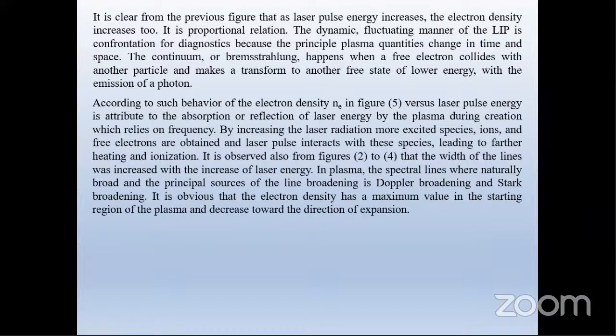It's a proportional relation. The dynamic fluctuation manner of the laser-induced plasma is a challenge for diagnostics, because the principal plasma quantities change in time and space. The continuum or bremsstrahlung happens where a free electron collides with another particle and makes a transition to another free state of lower energy with the emission of a photon. This behavior of the electron density in figure 5 versus laser pulse energy is attributed to the absorption or reflection of laser energy by the plasma during creation, which relies on frequency.